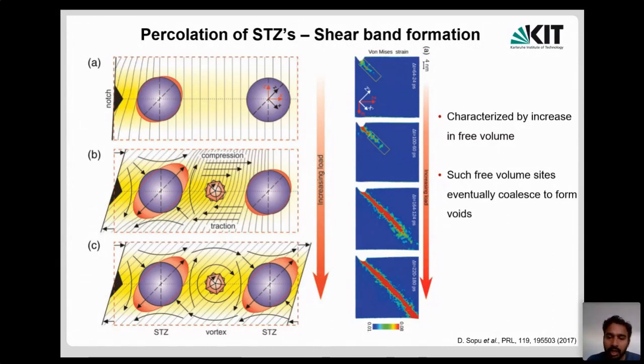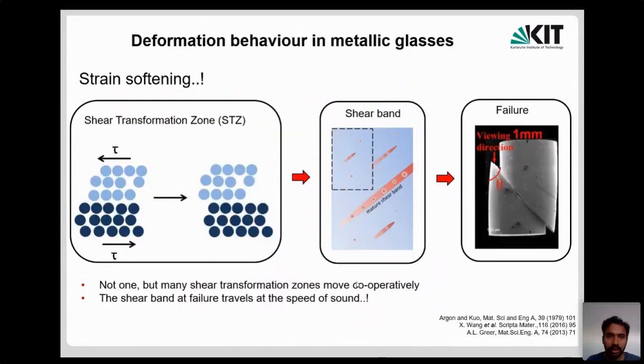So that's what happens here also, that when you have these shear bands forming, they create a lot of voids, and the void formation is what is giving no ductility for the metallic glass at all. So this is a very important information to carry on. And once you get that, and finally, you'll have failure. So in a nutshell, this is how the deformation progresses.